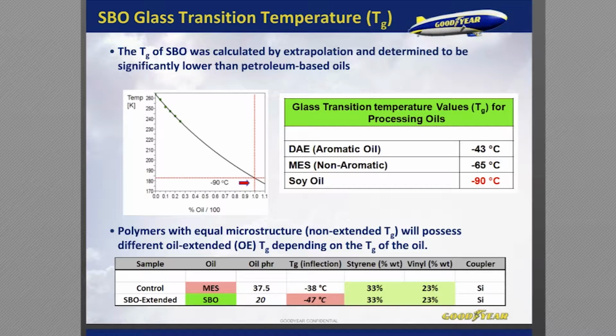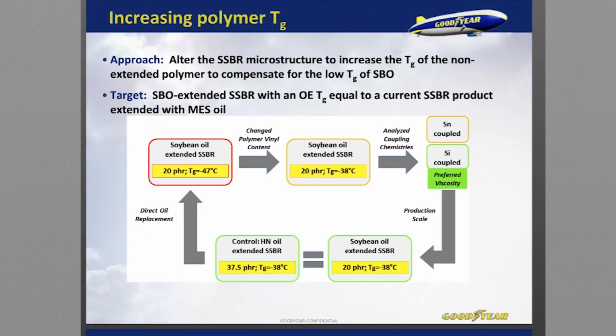And here's a quick comparison of an identical polymer microstructure. We took this commercial polymer cement and added oil to the cement, and you can see here in this TG inflection column a significant shift in the glass transition temperature of the extended polymer when petroleum-based oil was substituted with soybean oil. So why is that important?